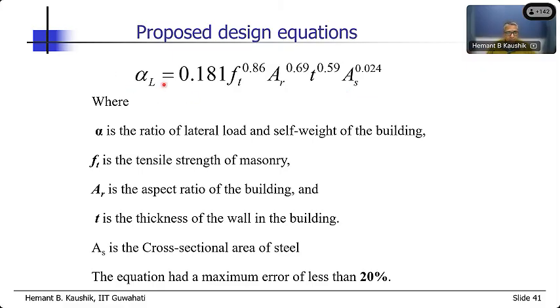So alpha L is basically the ratio of the lateral load to the self weight of the building. So you can directly compare it with the seismic coefficient that is given in IS 1893. So they are directly comparable. And when we compared it with the experimental results, the error was about 18-19%, which seems to be high, but then those who work on masonry, they will appreciate that this 20% error in masonry is very, very low. Because masonry is a very uncertain material.